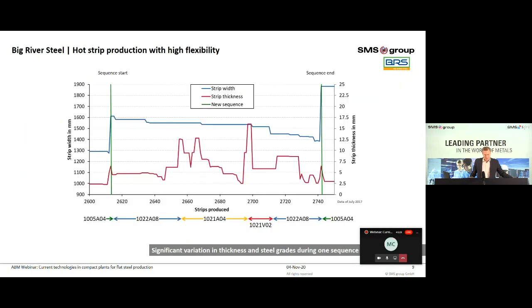An example for the production flexibility of Big River Steel is shown on this slide. As a newcomer in the steel business, Big River Steel had no existing customers, and they have to directly produce the orders. Due to this fact, the CSP plant could show its full flexibility. The green vertical lines are showing the start and the end of the production sequence. Considerable thickness changes with a maximum 17.5 millimeters and a minimum 2.5 millimeters were made in this sequence, together with 3 steel grade changes.